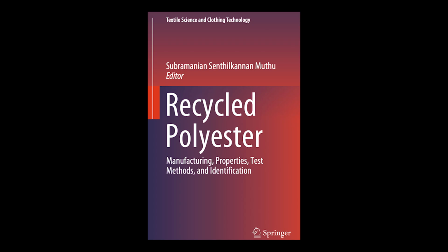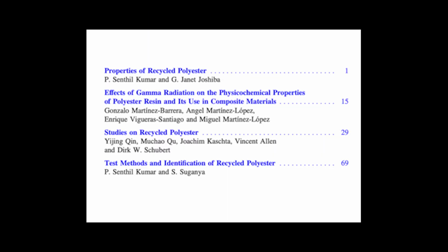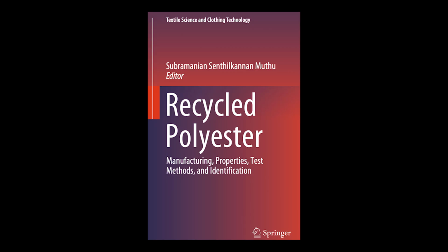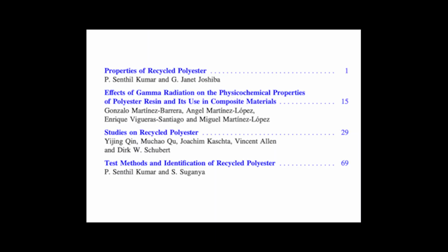Water. How dry does it need to be? Incredibly dry. The limit is generally accepted to be below 0.02% water content. That's just 200 parts per million. Wow, okay. 200 parts per million, that's tiny. It is. If you have high water content during reprocessing, especially during melting, it immediately triggers what's called hydrolytic degradation. Hydrolytic meaning water breaking it down. Exactly. Water molecules attack the polymer chains, causing more chain scission, drastically reducing the material's molecular weight and thus its strength. You basically start degrading the material before you've even finished processing it.